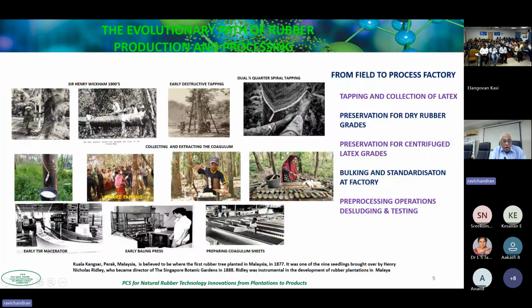And here you see, after we've done the tapping on the lower panels, we now tap the top panels so that we get a total of about 30 years of tapping from one tree. And once a lower panel is fully tapped and there's no yield, we move to the higher panel and tap, and we can even do stimulation at the top so that we get good yields. And this is how they make the coagulum.